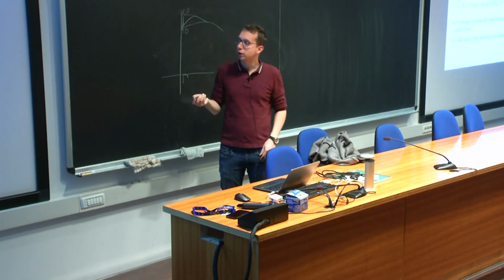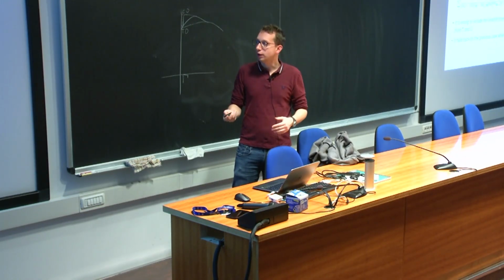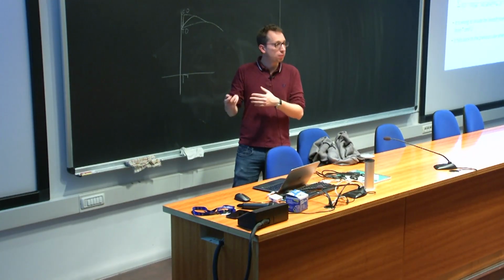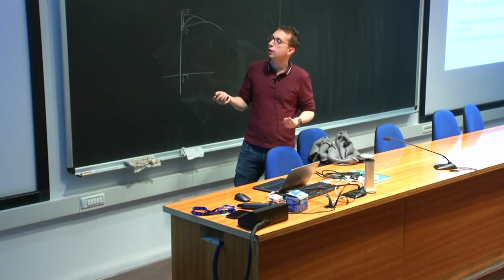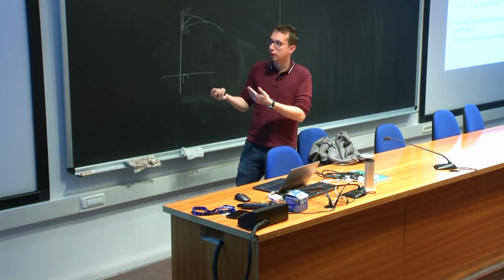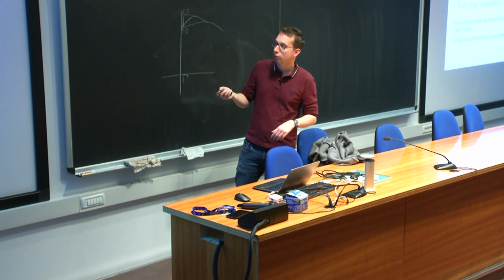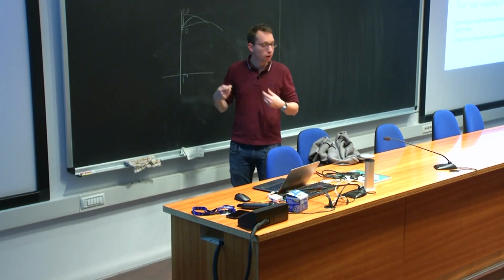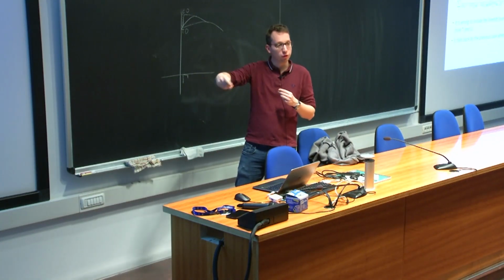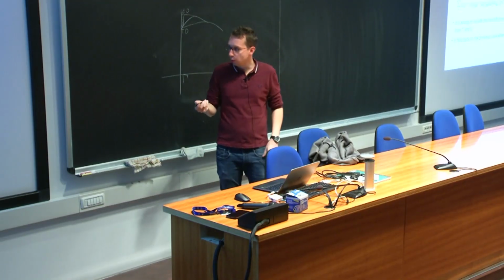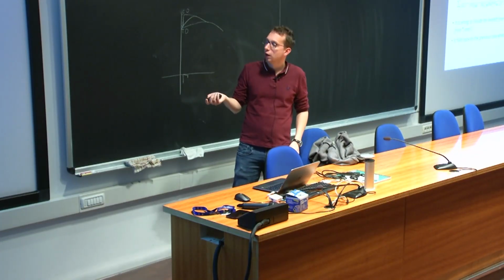For materials which are more anharmonic, instead of computing a line width associated with a certain phonon, you say, okay, it's the phonon itself which is not a good quasi-particle for my system. And so what you can do is compute the spectral weight directly, which is this expression, which is more or less the imaginary part of the diagrams summed over the phonon modes, and which gives you a spectrum of the phonon as a function of the energy, which is what you can actually measure by Raman or by NMR, or by neutron scattering.